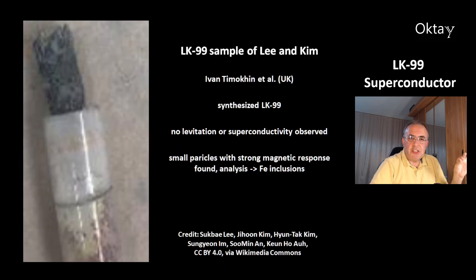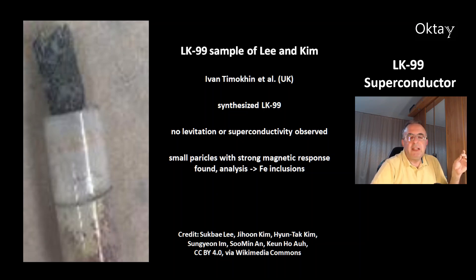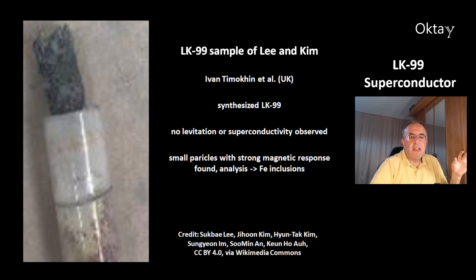This is an original picture from Lee and Kim of a sample of LK-99. There is another scientist, Ivan Timokhin, and his colleagues from the UK. They also synthesized LK-99, but could not observe levitation or superconductivity. However, they found small particles with a strong magnetic response, and the analysis showed that these particles were iron inclusions.